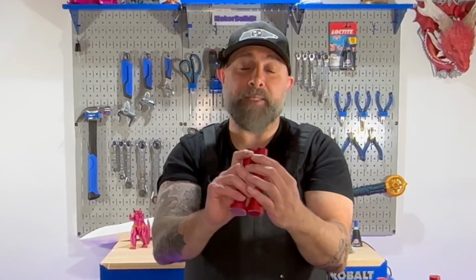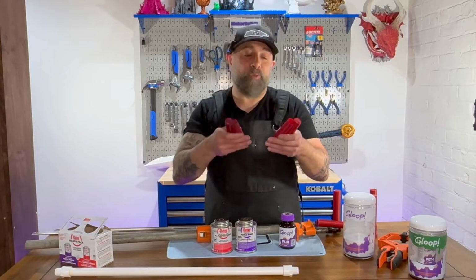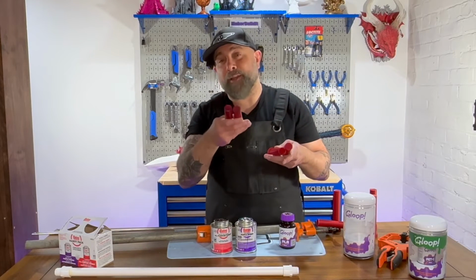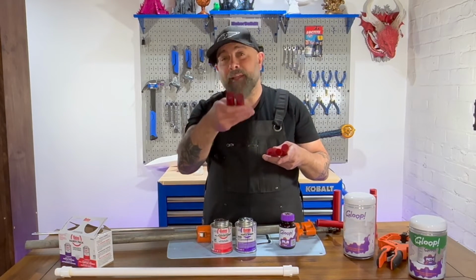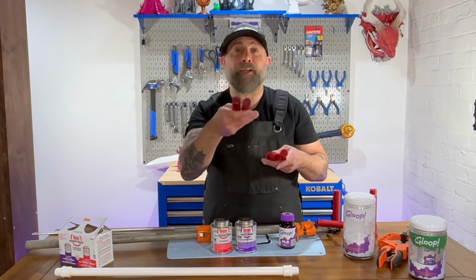Now this one's with primer on both sides and the PVC cement. Okay, and same thing happened. So basically you could see it did start melting the PLA a little bit. I don't know if you guys could see that, but the actual adhesive bond broke, not the PLA. So what's the conclusion? No matter how I tried using the PVC glue, the adhesive actually broke.